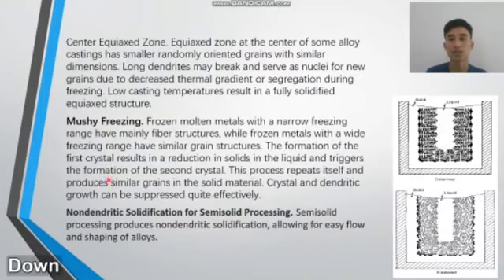Next, center equiaxed zone. The equiaxed zone at the center of some alloy castings has smaller, randomly oriented grains with similar dimensions. Long dendrites may break and serve as nuclei for new grains due to decreased thermal gradient or segregation during freezing. Low casting temperatures result in a fully solidified equiaxed structure.